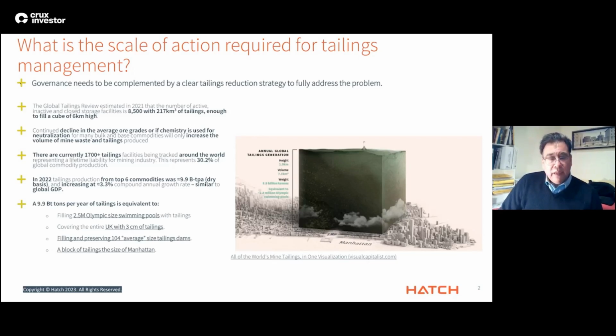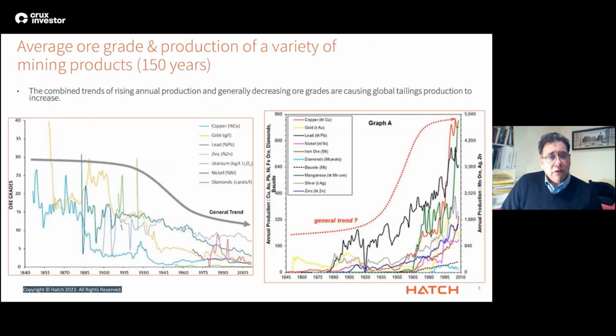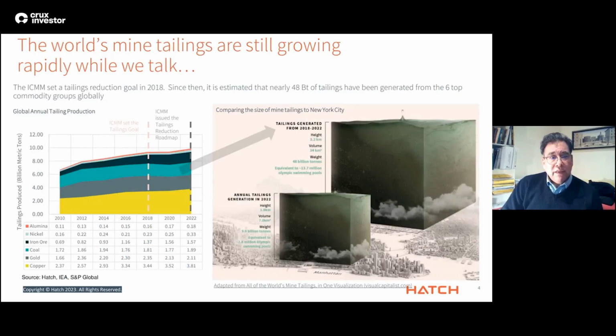And what we know that happens today in the mining industry is that there is a general trend of declining ore grade, and of course, miners have found out that you have to produce more. It's almost a given that you have to produce more to come up with the same amount of materials and metals in the industry. So invariably, you end up with a larger problem with tailings produced with lower grades. If we take a subset of metals in the industry, going from alumina, nickel, iron ore, coal, gold, and copper, the issue of generation of tailings is mostly driven by copper, gold, and coal, in terms of scale, but also in terms of the complexity of containment. You might find that residues and other tailings can actually be detrimental to the environment as well, if not properly contained.